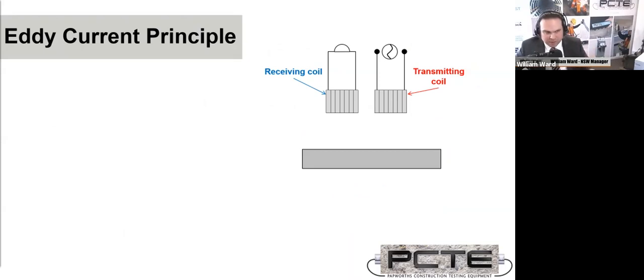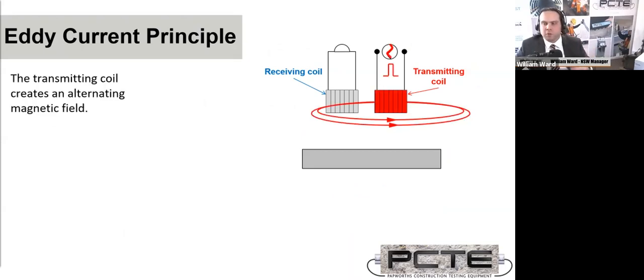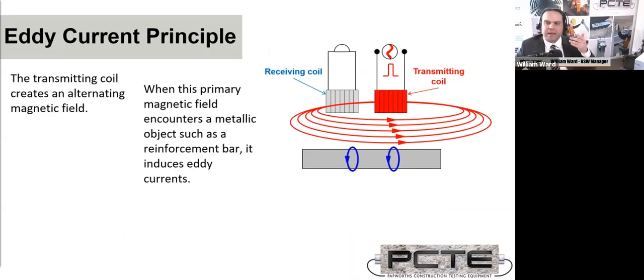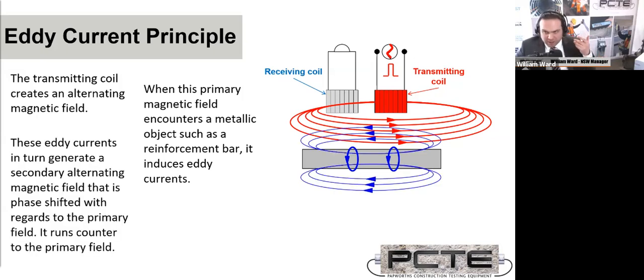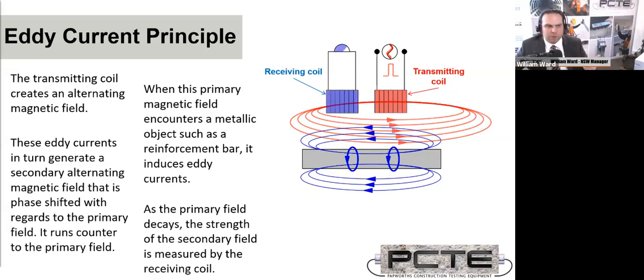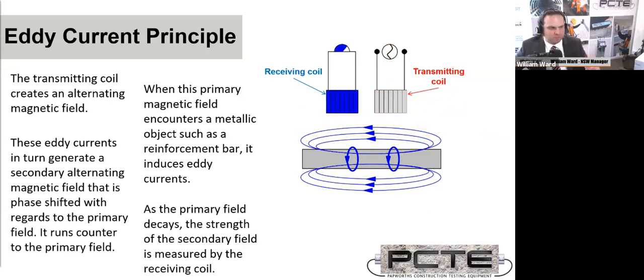Just to represent that in another way, we'll produce a pulsed current through the coil. It'll produce an electromagnetic field, which will induce current into the reinforcing steel. And that will produce its matched electromagnetic field, the strength of which will be measured by a second receiving electromagnetic coil. And by essentially comparing diameters of reinforcing bar expected to signal strength received, you have depth.